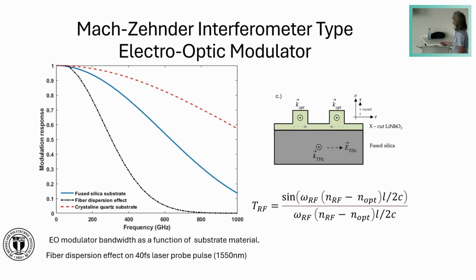This is a diagram which shows how the modulator response depends on the materials used. We have the substrate. We see the modulator response for a fused silica substrate versus the modulator response for a crystal quartz substrate. What is happening here is that the thickness in the two layers is very different, almost a factor of 1,000. The fused silica has a 500 micrometer thickness. The thin film lithium niobate is 600 nanometers. So the ratio in thickness is roughly 1,000.